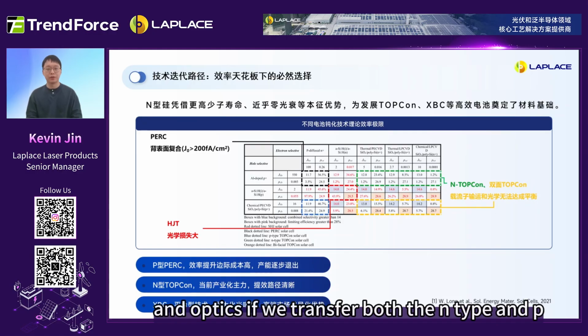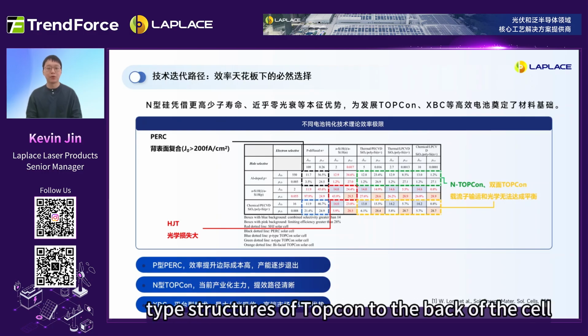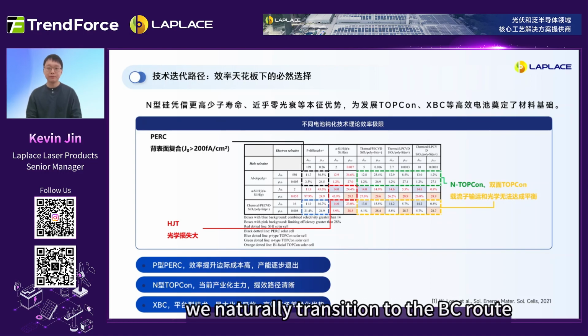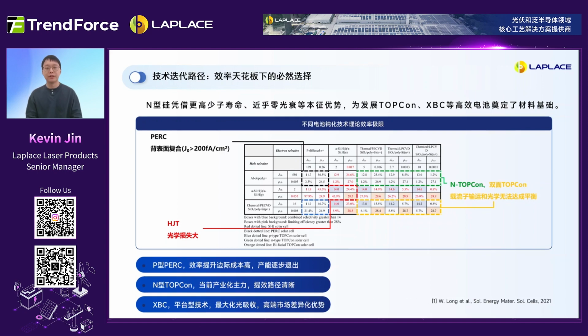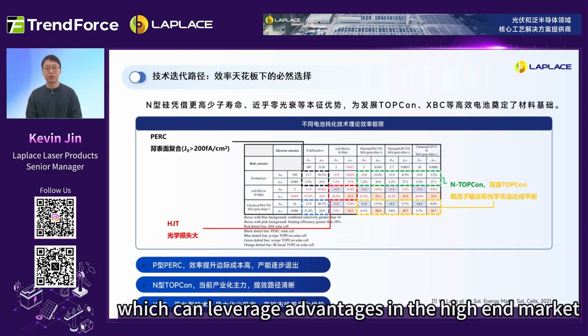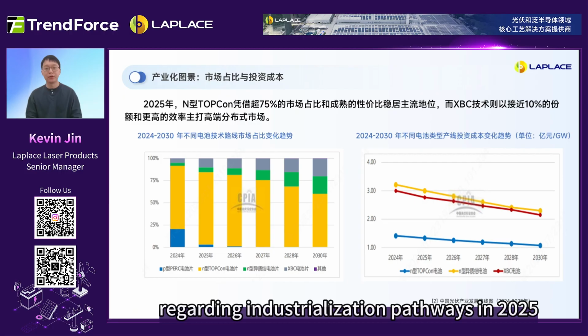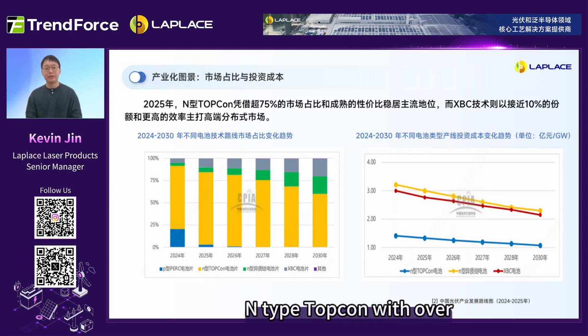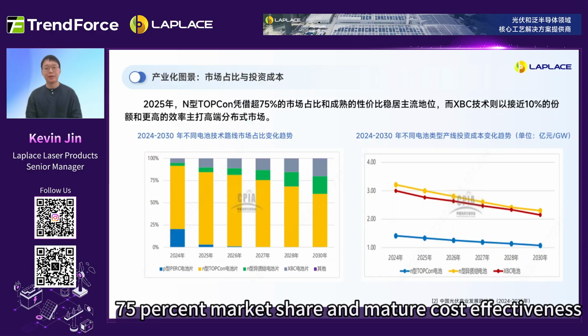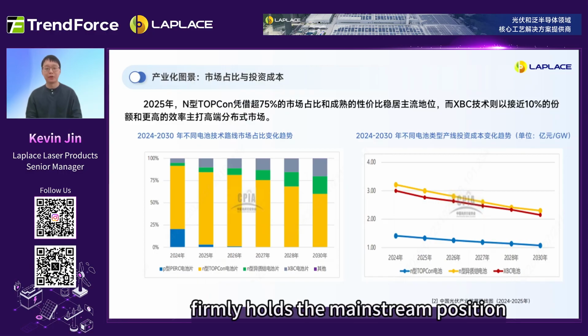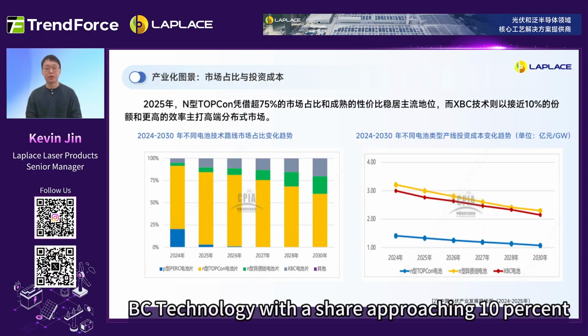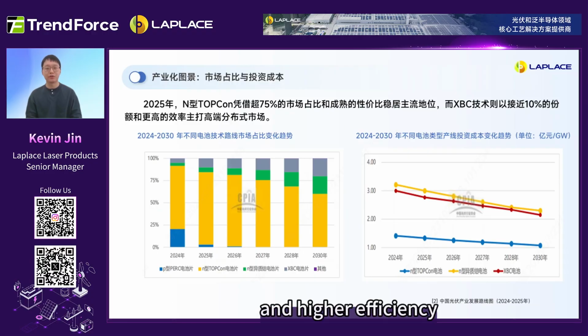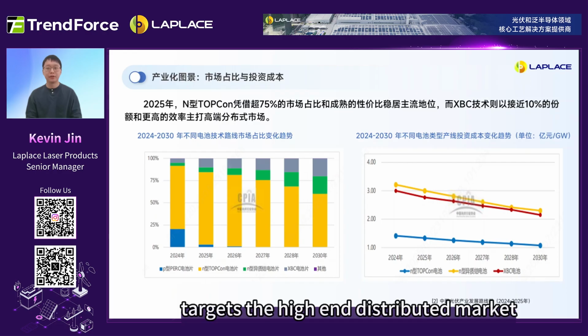If we transfer both the N-type and P-type structures of TOPCon to the back of the cell, we naturally transition to the BC route. Through the BC platform technology, optical absorption can be maximized, and the conversion efficiency upper limit can reach 29.1%, which can leverage advantages in the high-end market differentiation. Regarding industrialization pathways, in 2025, N-type TOPCon, with over 75% market share and mature cost-effectiveness, firmly holds the mainstream position. BC technology, with a share approaching 10% and higher efficiency, targets the high-end distributed market.